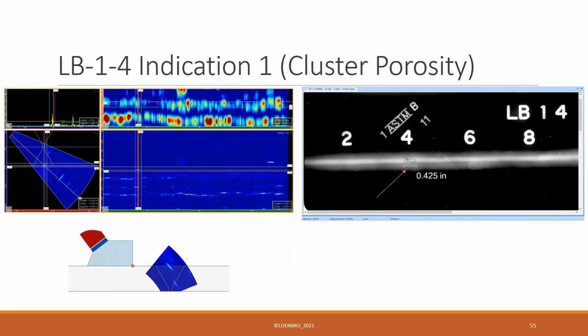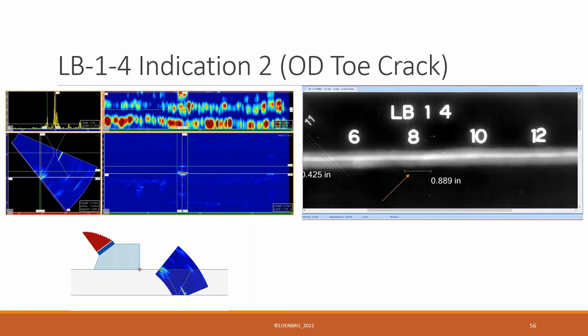When you look at the specific comparison, what radiography missed is what we actually expected it to miss, and I've got some images and data to prove it up. So sidewall lack of fusion, toe cracks or cracking in general, again, sidewall lack of fusion, sidewall lack of fusion and crack. It easily detected the other ones. Even though phased-array detected the porosities and the slag, as you'll see when I go, I'm going to highlight some of those in particular, you'll see that it was such low amplitude, a lot of times it's going to be so low that it's not even going to yield us to evaluate these discontinuities. So let's look at a few, and here's one to start with. So this is some clustered porosity. You can see it on the radiograph here. We detected it in the phased-array image. Very weak signal. You can see it as a 3D that I've kind of turned into a 2D to help it make sense to you. So here's your groove weld and very faint signal. So even though it detected it, that was actually for this criteria that we used for acceptance, it was below the evaluation threshold. So we know that it's detected, but we'll compare the susceptibility here in just a minute.